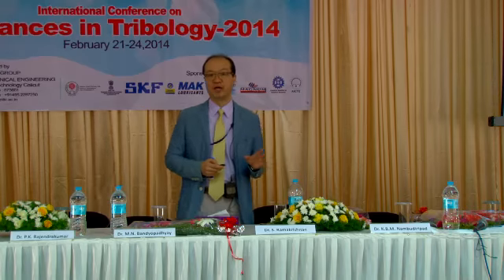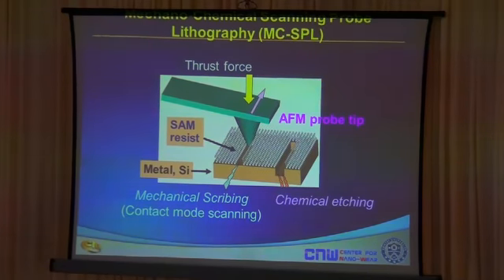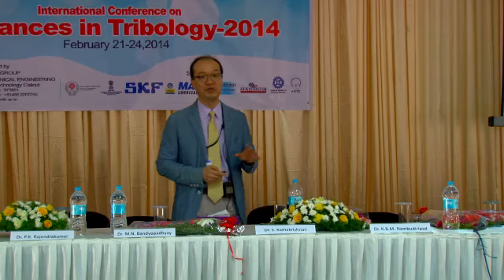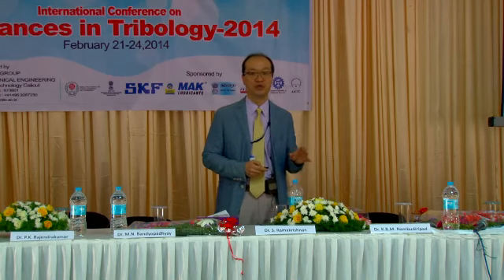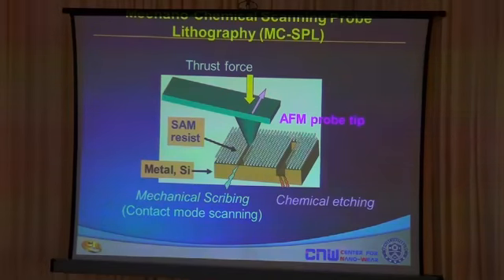We use the same AFM, but we do not use the AFM to machine the substrate directly because the tool will wear out. On the substrate, we coat the substrate with a very soft material, in this case a self-assembled monolayer. It's an organic film. We use an AFM tip and we program the AFM tip to remove the self-assembled monolayer at locations where we want the pattern to occur.